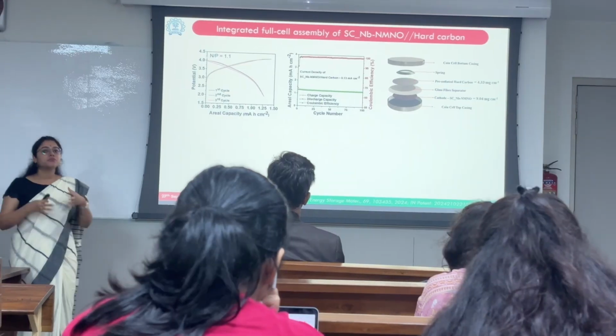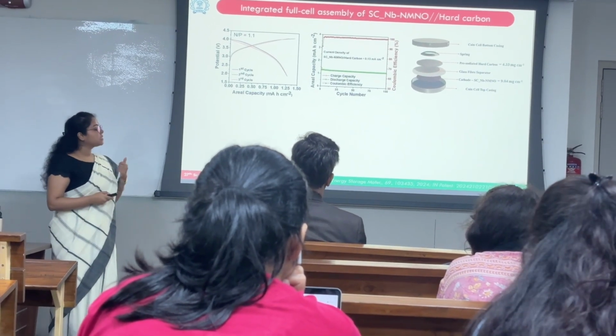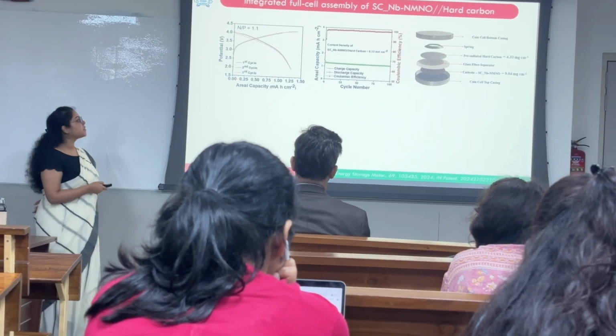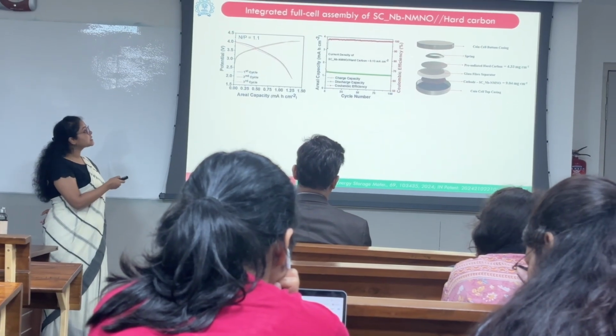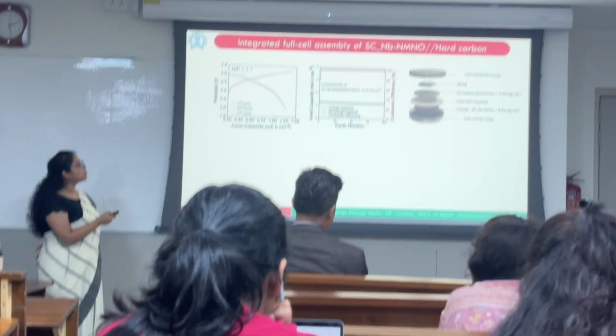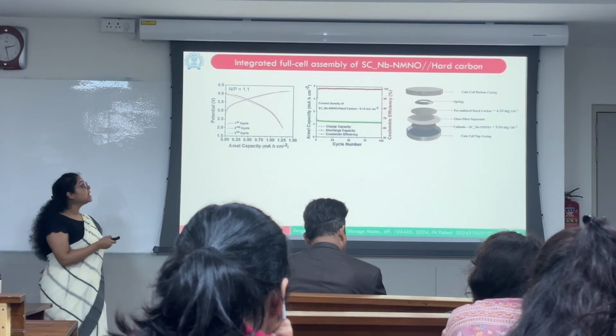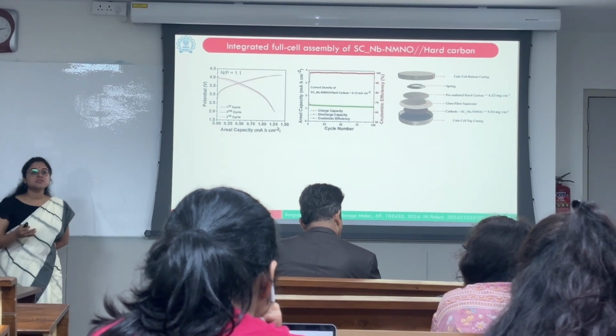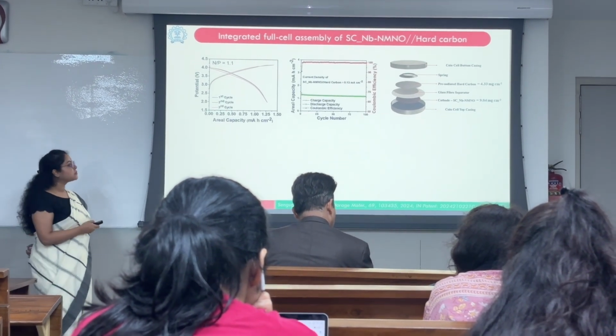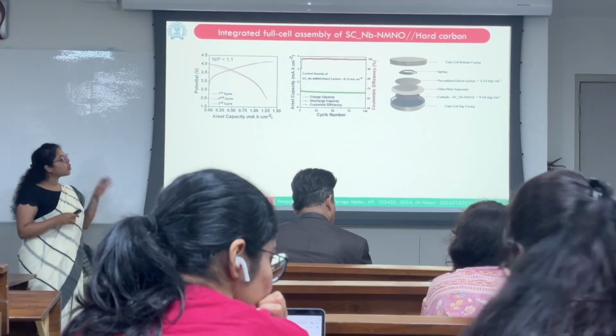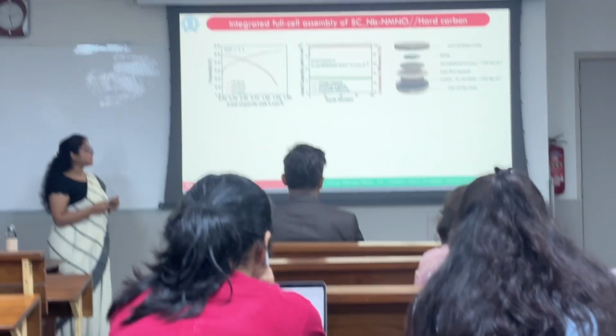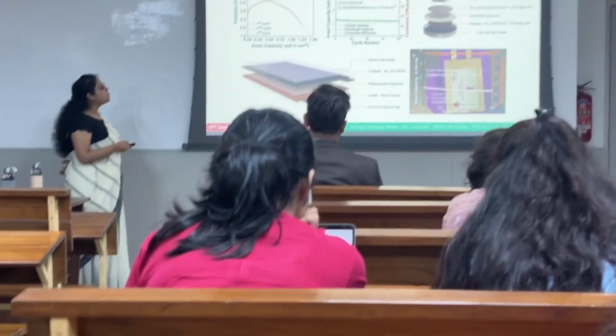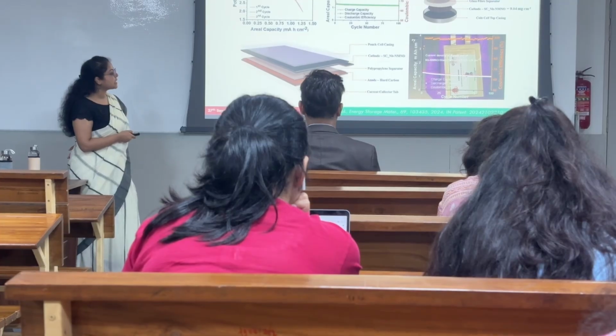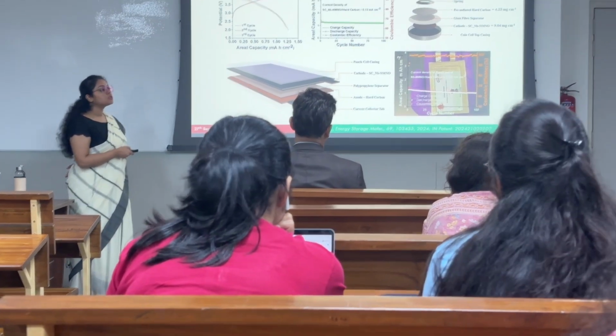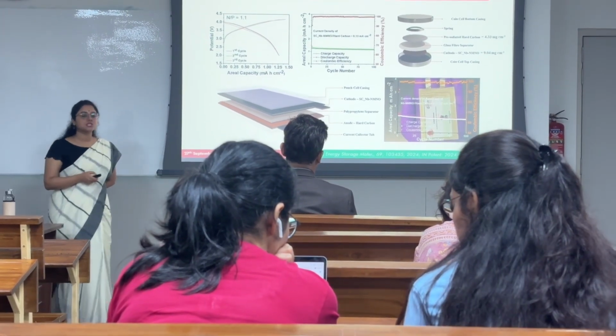So we integrated a full cell out of it as well, and we considered the pre-sodiated biomass derived hard carbon, and when cycled at a current density of 0.13 milliamp per centimeter square, we saw that it gives us a capacity retention of around 93% after 100 cycles. And when we optimized it in the coin cell, we also fabricated a single layer pouch cell, which also gave us a capacity retention of around 86% after 100 cycles at a current density of 0.109 milliamp per centimeter square.